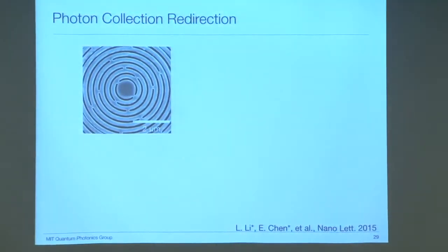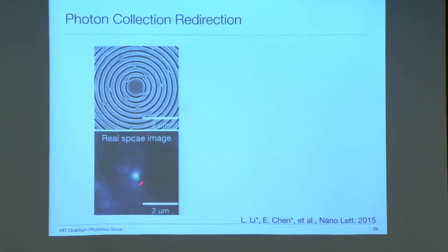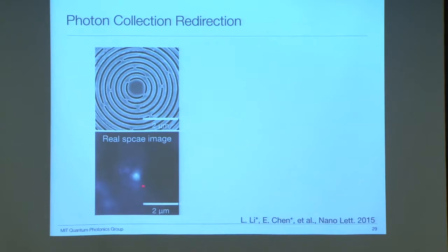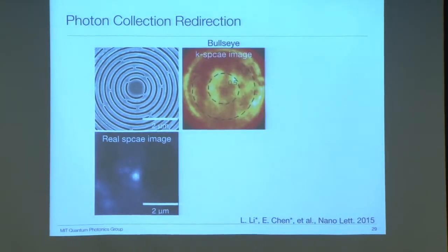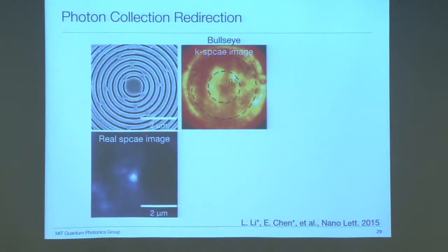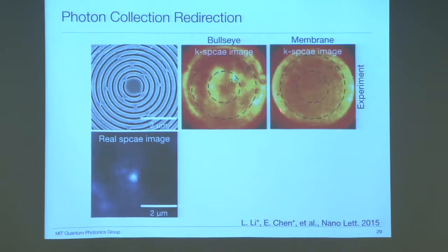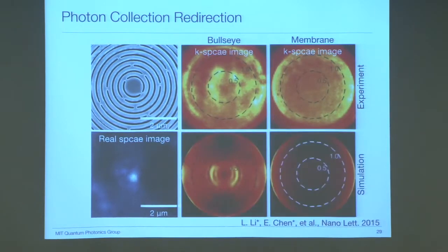This is a SEM image of the resultant bullseye gratings. The photoluminescence shows us this bright spot, which was confirmed to be a single NV center by both second-order autocorrelation measurement and spectral measurement. We also analyzed the bullseye's far-field mode pattern. As you can see, there is strong intensity within a numerical aperture of 0.7. Comparatively, for an unpatterned diamond membrane, the photon emission is primarily into the higher NA mode. The simulation results are also consistent with these experimental results.